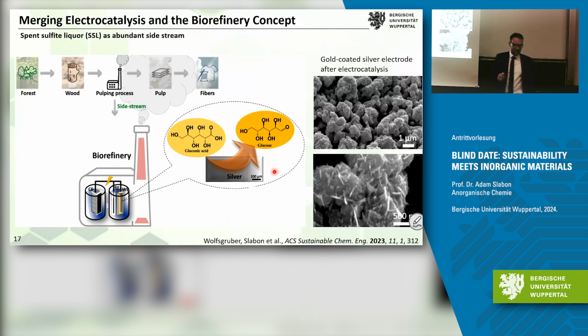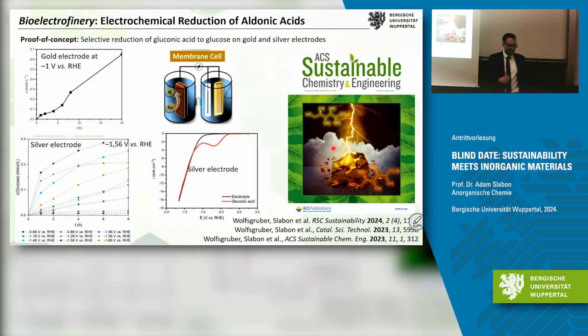She could get a gold-coated silver catalyst, and this was actually quite successful in valorizing this feedstock. So you can see, as a function of time against -1 volt, that you are increasing the glucose concentration. You need a tandem cell, which has a membrane in it. Without the membrane, you get decarboxylation of your product.